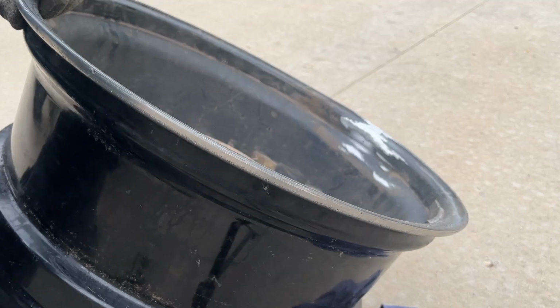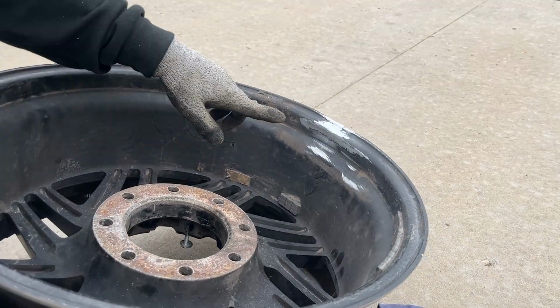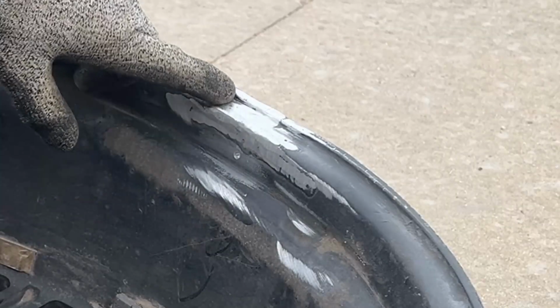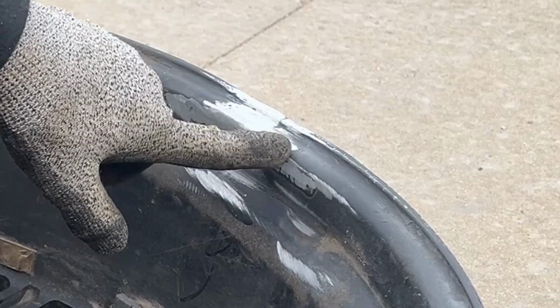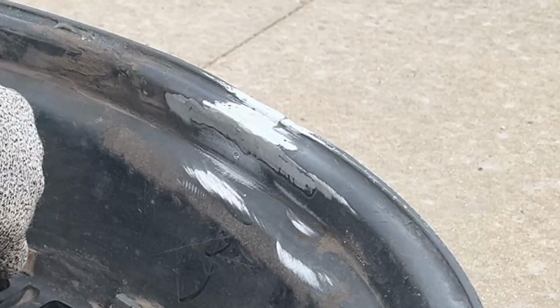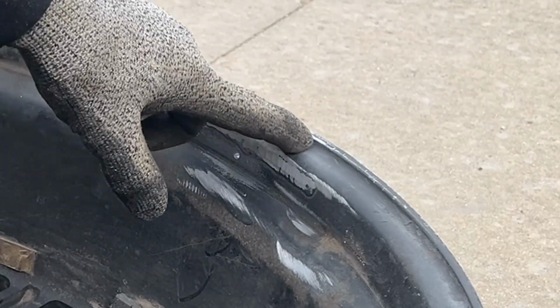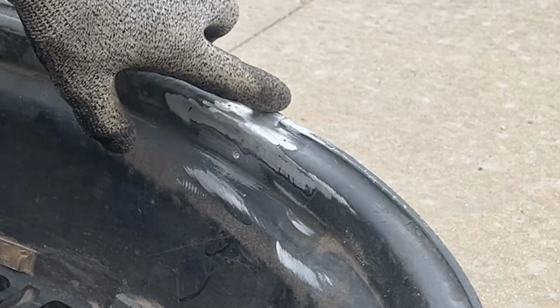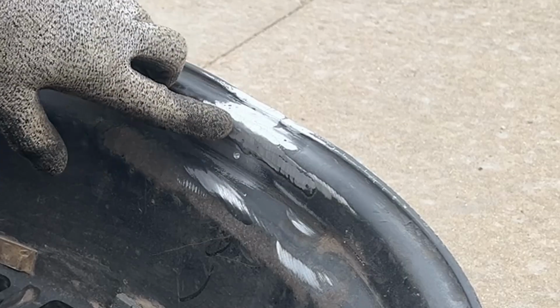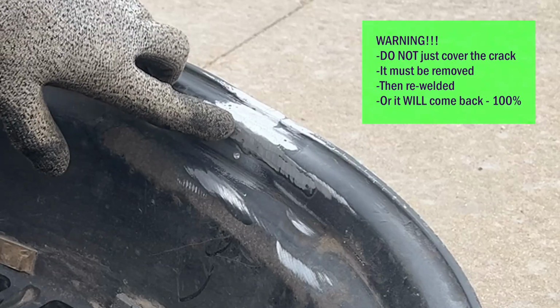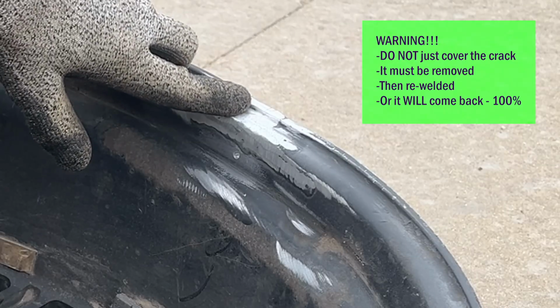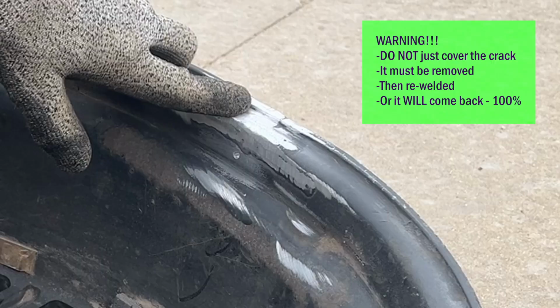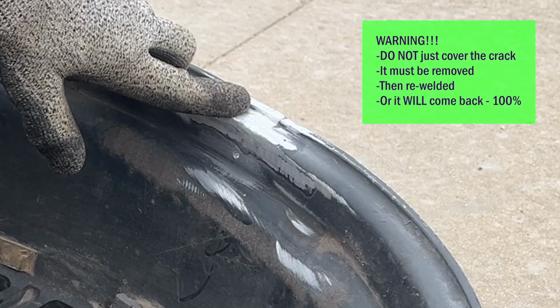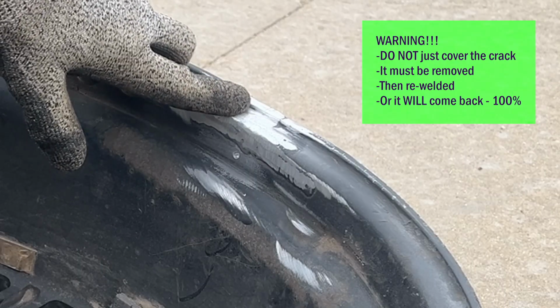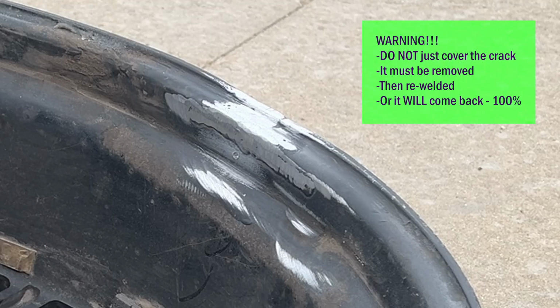All right, we got to get down in there just a little bit more, right down into there. And what I'm trying to do is not take too much wall thickness off anywhere that wasn't welded, right? So we're going down to the original base metal, and I'm being a little bit cautious because I'm going to eat right through that weld. You may be tempted to just cover that weld up with weld, right? To just cover that crack up with weld. Don't be tempted to do that because it's going to crack right in the same exact spot. If you don't remove the crack, it's only a matter of time before it propagates back through the new weld.